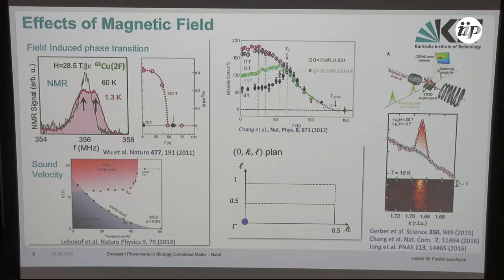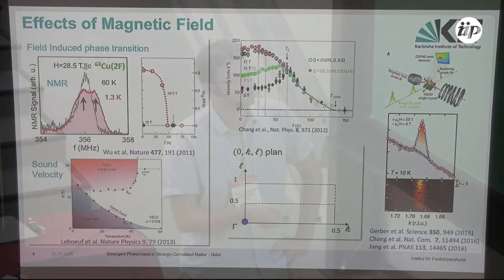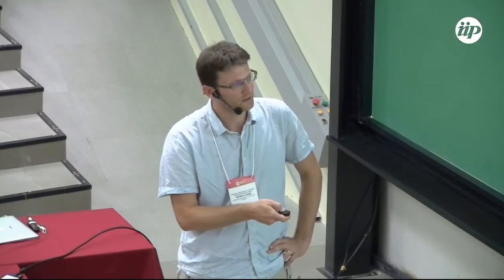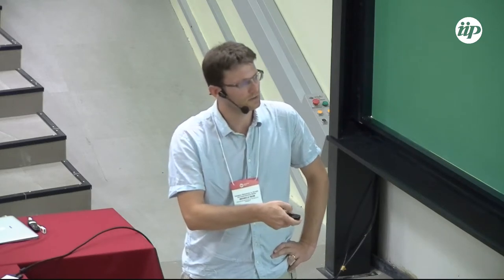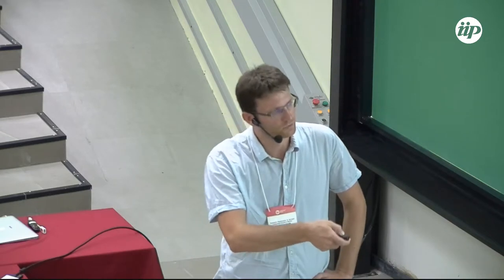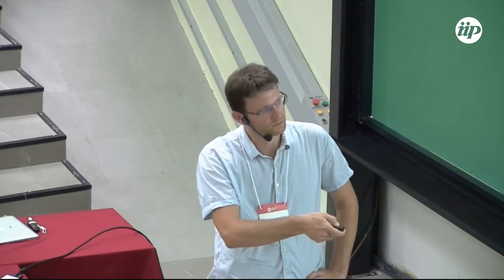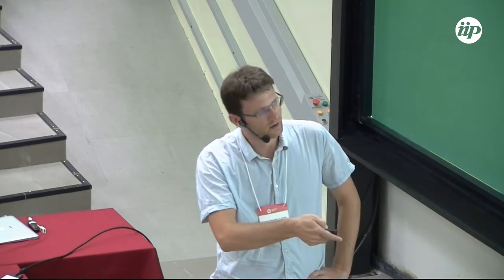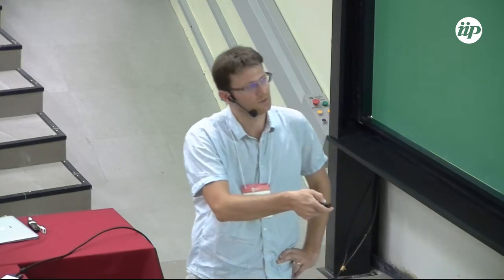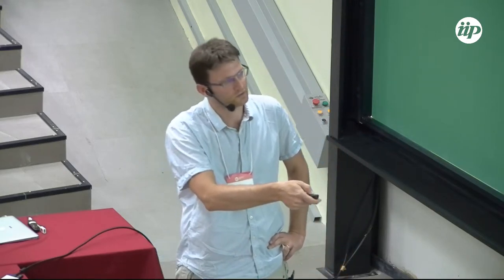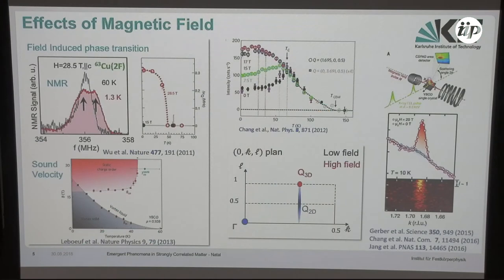So if I plot the situation in the HKL plane here, I have my gamma point. At low field, I have the 2D wave vector. So it's almost a rod along the C-axis, but with some kind of doubling of the unit cell along the C-axis. And when I apply a high magnetic field, a very sharp, bright reflection appears here, and it corresponds to a 3D order at L equal 1, but with the same in-plane incommensurability.